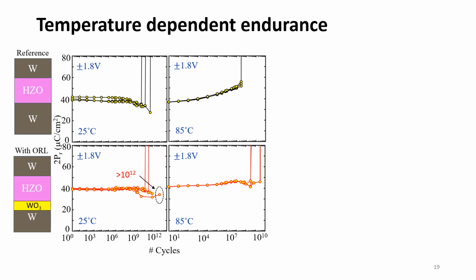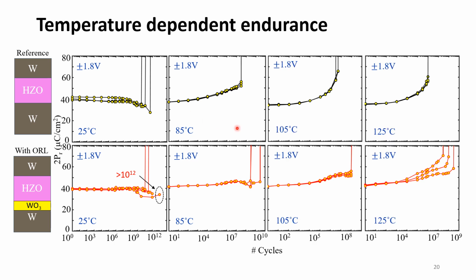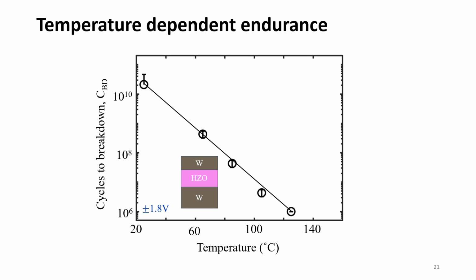Next, we did the same measurement at 85 degrees Celsius, 105 degrees Celsius, and 125 degrees Celsius. And we could see that in each case, the ORL device has higher endurance compared to the reference device. To summarize these data, I have plotted it in a different way. Here you can see the x-axis is temperature and the y-axis is cycles to breakdown, or the endurance of this device. For the reference device, as we increase the temperature, the endurance degrades very fast.